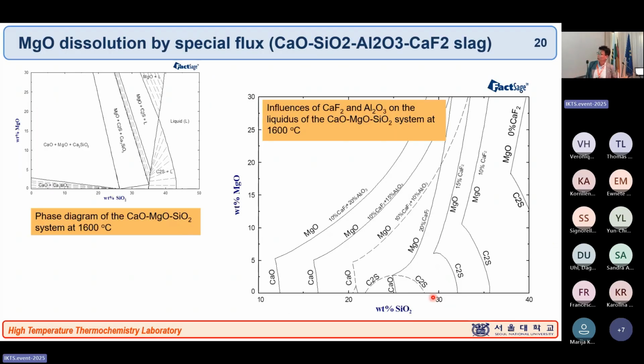And now this is another example with the alumina and the CaF2. So in the CaO-SiO2 with the MgO. This is the rectangular diagram of the CaO-MgO-SiO2. Here is SiO2 concentration. This is MgO concentration. So this is C2S saturation I showed you before in the ternary triangle diagram, and this is MgO saturation. So this is the point we want to keep our slag to maximize refining capacity plus minimize refractory dissolution.